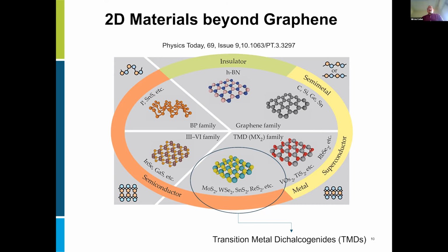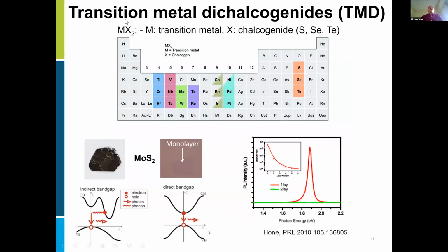So transition metal dichalcogenides basically have a formula like MX2. M is a transition metal, which can be found in this group here. X is a chalcogenide: sulfur, selenium, tellurium. Some of these materials, when they are exfoliated from bulk into the monolayer, you can see here, if you squint, you can see a monolayer, they show what is known as an indirect to direct band gap transition.